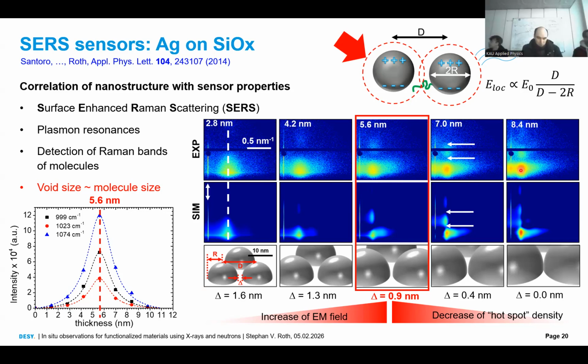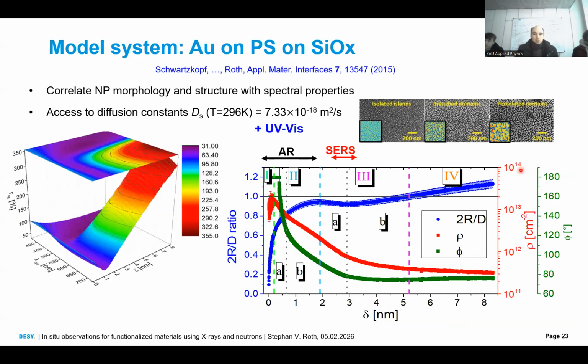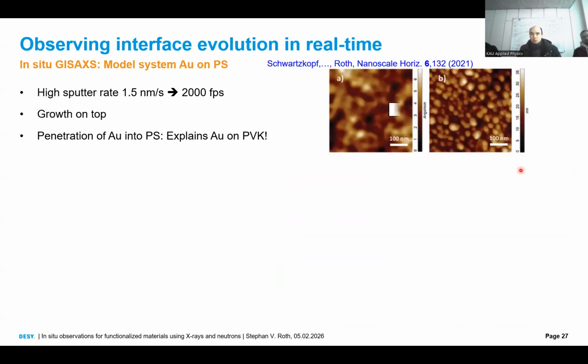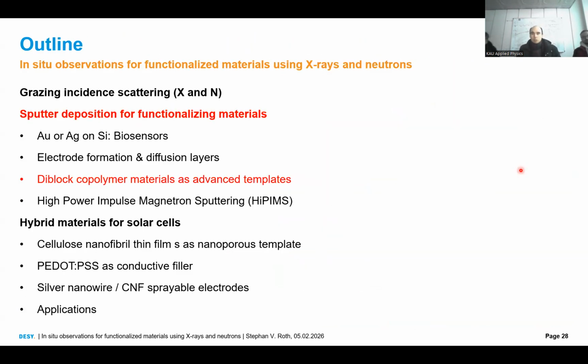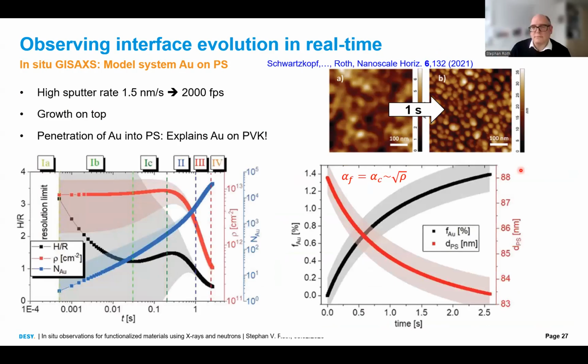One more very small question. Slide 28, about gold. 27 then. You can measure essentially by GISAXS how deep the gold is going. How do you confirm it? Do you just take the sample out and measure, so not in situ, right? And with which methods? So we did XRR on this, and we find also this enrichment layer.